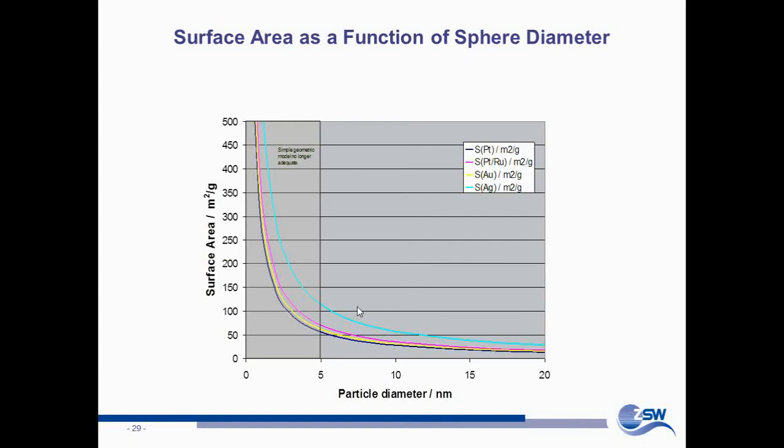In colloid science, what we learn, those nanoparticles are affected if they are separated. You produce a nanoparticle, you leave it there, they get together, become big particles. You no longer have the effect of nanoparticles. That's the reason why we support those nanoparticles on the surface of porous carbon, in order for them not to find their way to each other.